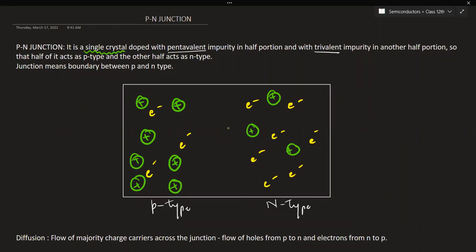Two separate semiconductors cannot have a continuous contact at the atomic level. The junction will behave as a discontinuity for the flowing charge. So both acceptor and donor impurities must be grown in a single crystal. This can be silicon or germanium. So P-type or N-type silicon crystal can be obtained by adding acceptor or donor impurity into the silicon melt while growing the crystal.